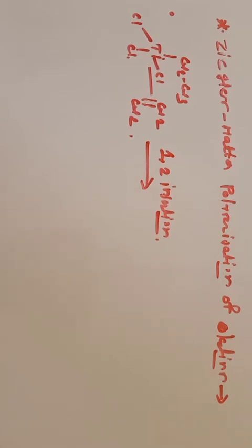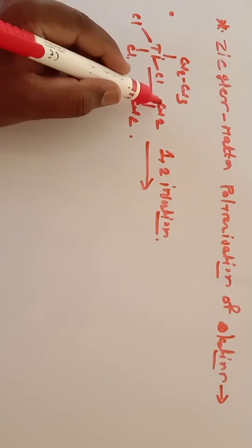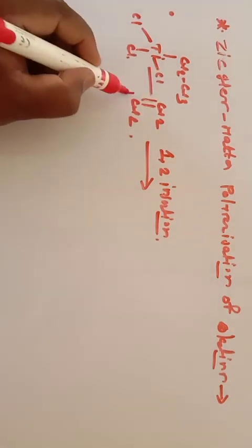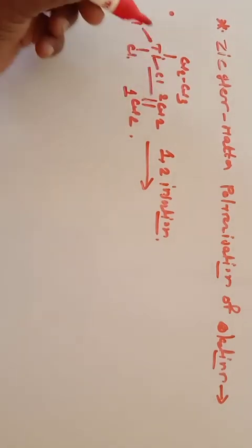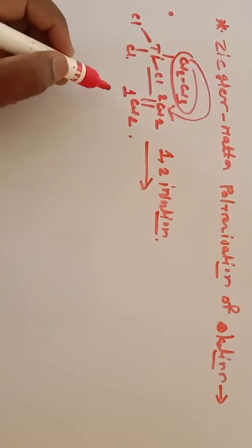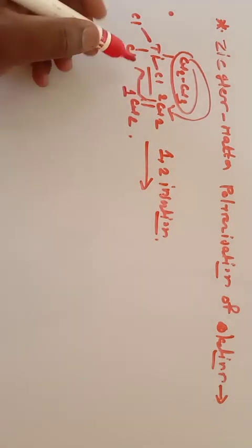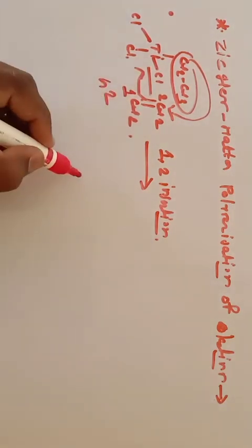So this 1-2 insertion reaction results in the formation of a new bond, in which this ethyl group is shifted from this titanium atom to this carbon number 2. Let us consider this carbon number 1, this carbon number 2. So this group is shifted onto this carbon, and the hapticity 2 is converted into hapticity 1. So in this case the hapticity of these alkenes is 2.